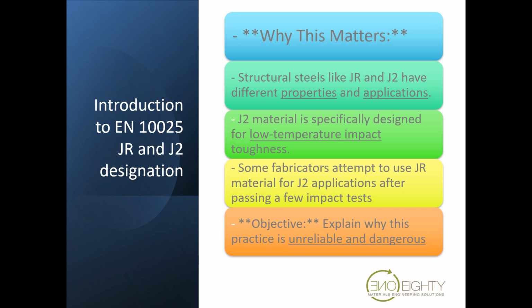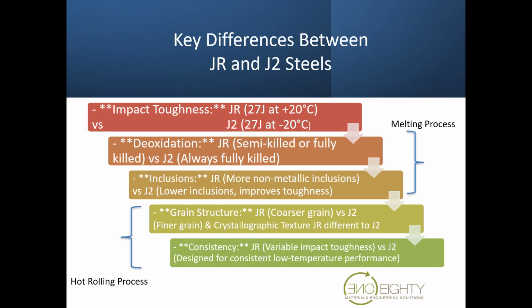But what we see in the industry is that some fabricators attempt to use JR material for J2 applications by simply buying some JR material, conducting a set of Charpy impact tests, and if they happen to pass the J2 requirement, miraculously the material is transformed into J2 material, which cannot be the case. What's even more disturbing is that sometimes the Charpy impact tests are done 4 or 5 times before a set is passed, and the fail tests are ignored. It's only the pass test certificate that's put in the dossier, and we magically have J2 material. Yeah, so I think that in itself is evidence that this really cannot work. It's nonsensical. But I'm going to explain to you the metallurgical reasons why.